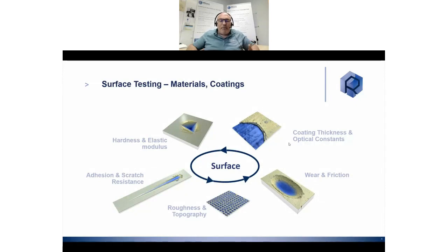In fact, we are proposing multi-functionality tools. And what we want to do is to offer the possibility with our tool not to do only one analysis, but to combine a lot of technology and a lot of measurement characterization. That's why, in the past, we started with wear and friction by tribology. After we had scratch testing, we added indentation, we added also a 3D microscope linked to the system for roughness and topography. And we also added spectral reflectance for coating thickness and optical constants. All the tests here can be combined on the same tool at the same time, and with this product, we can learn much more than only doing one test.